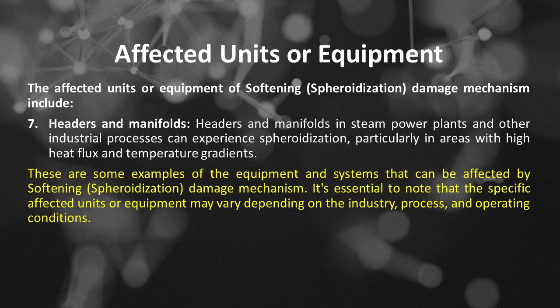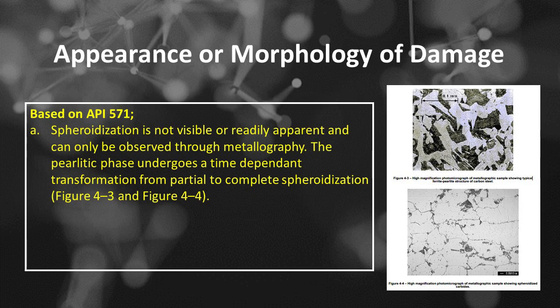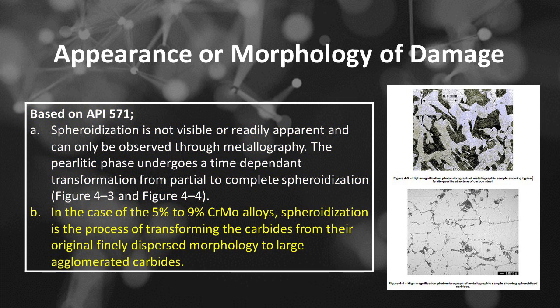and operating conditions. Appearance or morphology of softening or spheroidization damage. Based on API 571, spheroidization is not visible or readily apparent and can only be observed through metallography. The pearlitic phase undergoes a time-dependent transformation from partial to complete spheroidization, Figure 4.3 and Figure 4.4. In the case of the 5% to 9% CrMo alloys, spheroidization is the process of transforming the carbides from their original finely dispersed morphology to large agglomerated carbides.